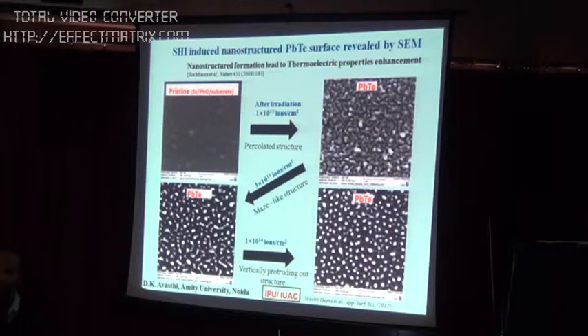And I said that the important thing was to have nanostructures in thermoelectric material. And there was a Nature paper, a Science Nature paper, by Hochbaum. He said that nanostructure formation leads to enhancement of thermoelectric properties. So we wanted to see what the morphology of our films is, and it was very nice to see that they were actually nanostructures. You can see in the beginning the film was like this. And then when you irradiate, you get this kind of structures which are basically nanostructures. So that means you are having a nanostructured thermoelectric material. It is supposed to have better qualities.